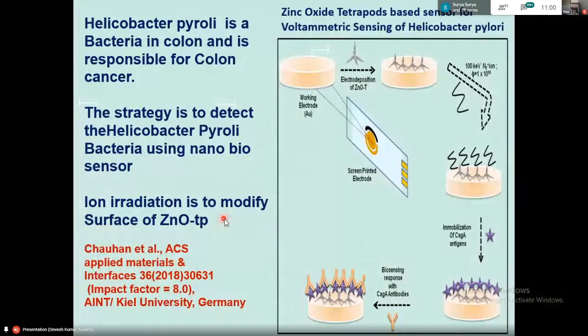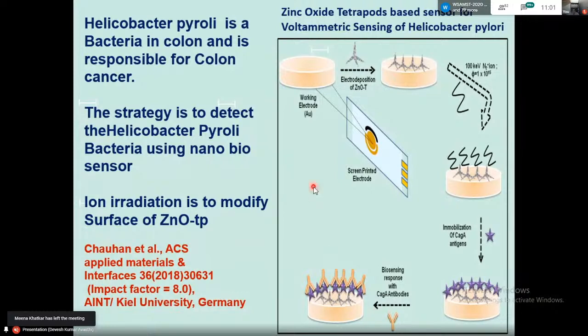Here we have shown that ion irradiation improves its sensitivity. This is a device which is just a finger-like thing, something like the glucose testing chips, the same size. In this area, we put the zinc oxide tetrapods, and then some irradiation is done, and then we attach and immobilize the antigens here, and then we put the blood serum, and it gives a signal that something is there. And we have tested this for selectivity also, that it is selective for Helicobacter pylori bacteria.